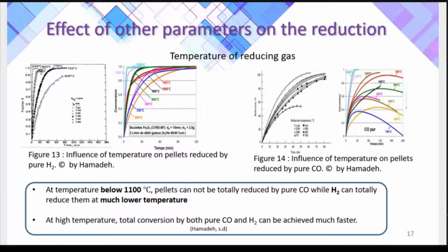This study also emphasizes the impact of the temperature of the reducing gas, because it studied the influence of the temperature of the reducing gas on the conversion rate of the pellet. It used mainly pure H2 and pure CO. We're able to observe that at temperatures below 1100, pellets cannot be totally reduced by pure CO, while H2 can totally reduce them at much lower temperature. At high temperature, total conversion by both pure CO and H2 can be achieved much faster.